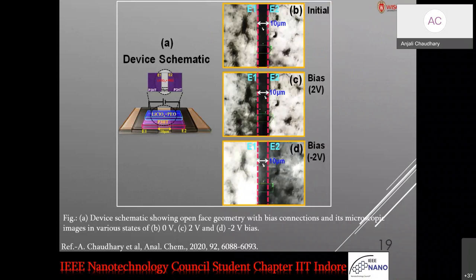And this is to explore how it is going on, why it is changing color. We fabricated an open device in which two gold electrodes are separated by a 10 micrometer distance, and then we spin-coat P3HT and lithium perchlorate plus PU. PU is a gel type of matrix. So we probe this, and then see under the optical microscope, and further we carry out Raman spectroscopy and microscopy to see how these color changes happen.